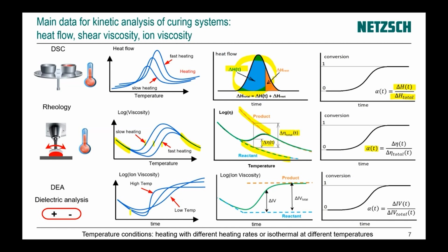Usually, the measurements are done with heating at the beginning, and then at different isothermal segments at different temperatures. For example, here we have a measured curve at low temperature. It goes very, very slowly, and then finally it has a higher value. We also have the measurement of curing at high temperature. It goes very fast and finally has a low value. Then for each curve, we can calculate the baseline for the reactant and for the product. Then we create a ratio between the current change of ion viscosity and the total change of ion viscosity and have the concentration. Finally, for each method, we have a conversion, and this conversion changes from 0 to 1 and shows us how the reaction goes on.